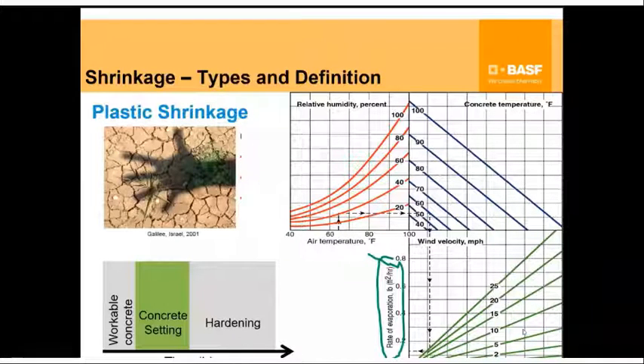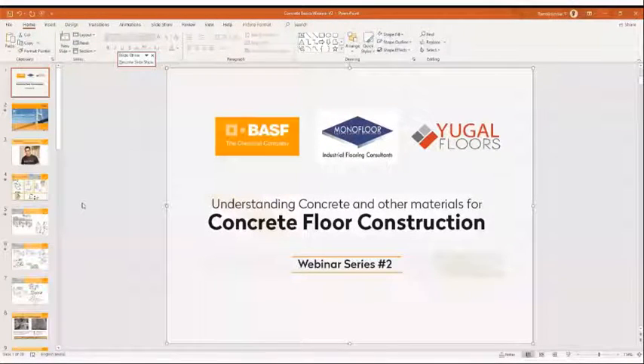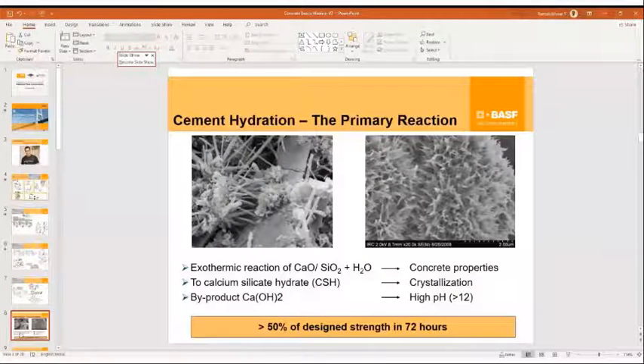So if we want to understand what is really happening, the little cartoon on the bottom left shows the timeline of concrete hardening, right? You first have workable concrete, then concrete setting, and then hardening. If you go along that path, the red line is the stress level in concrete. As the water starts to evaporate, nothing much happens in workable concrete, because it still moves around, so it's not a problem.